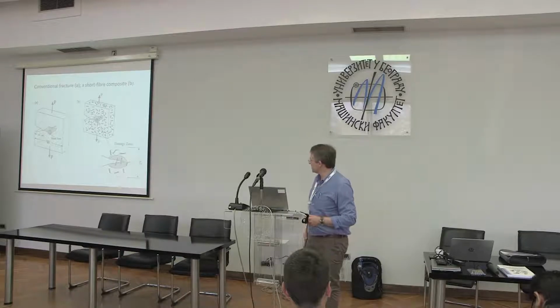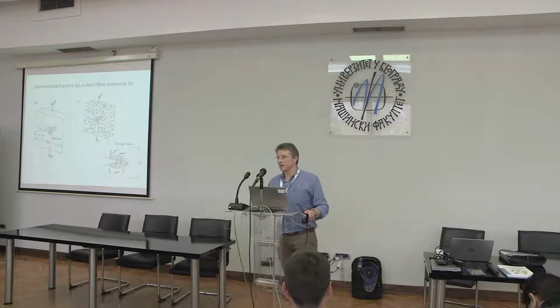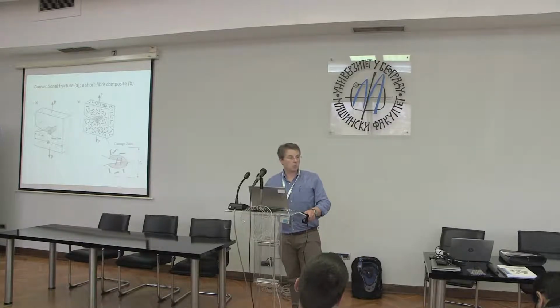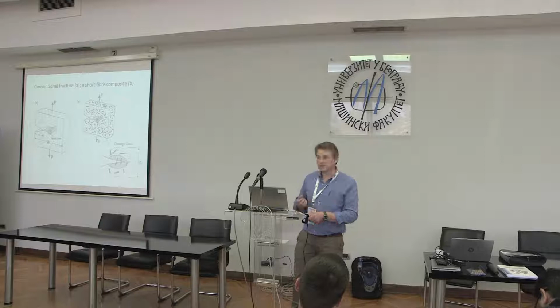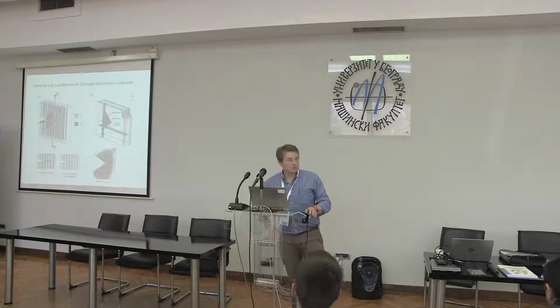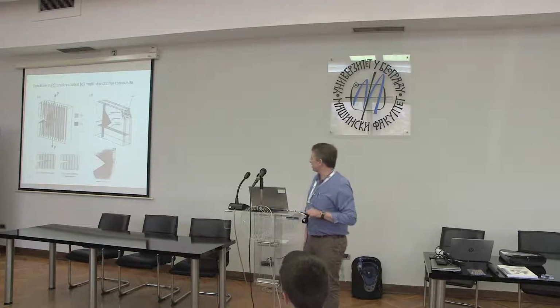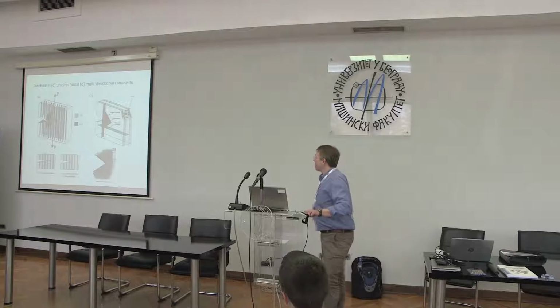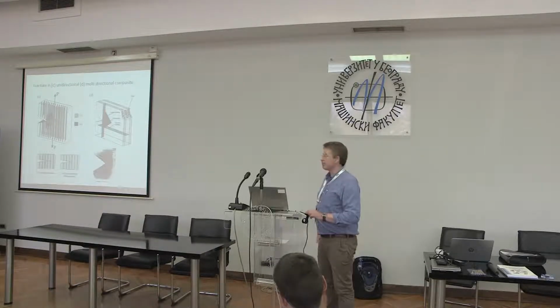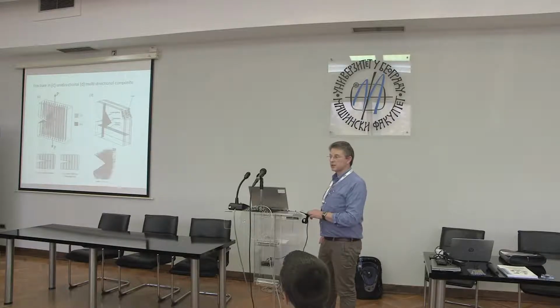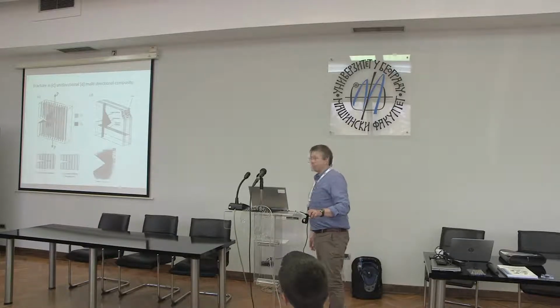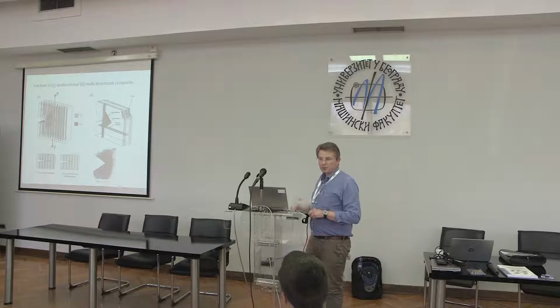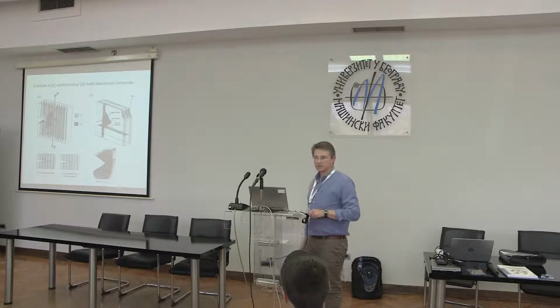And you can see there in the inset, we make the distinction between the damage zone and the plastic zone. And of course, one would expect, and one of the reasons we put those fibers in is to increase the size of that zone and to dissipate more energy. Moving to laminates, where we have, for example, layers of fibers embedded into a matrix, in this case an epoxy matrix, then of course if we introduce a sharp crack and we try and run a crack through that material, we know from what we know about the mechanical properties of fibers that the fibers are not going to tend to fracture. In fact, it's relatively difficult to get that specimen to transverse fracture.